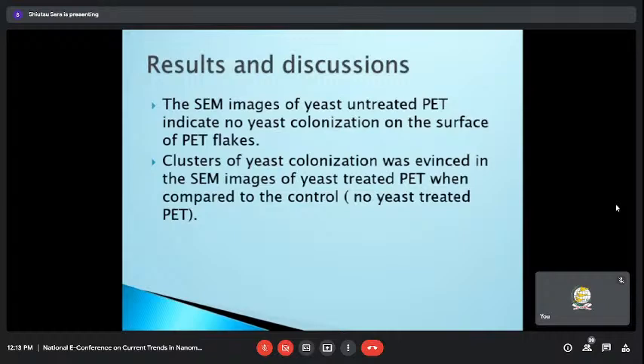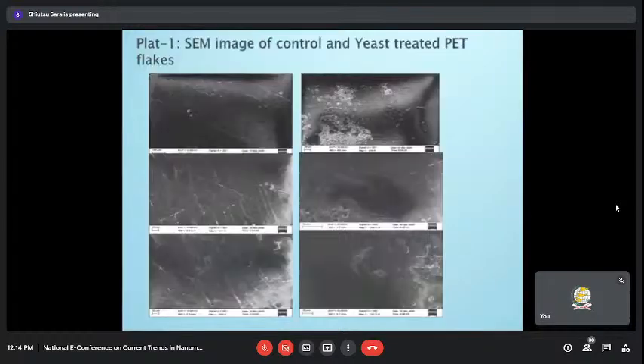Coming to the results and discussion, from the experiment which we have performed, from the SEM analysis method, we have found that there are two samples, one treated and the other untreated. The sample which we treated with the bacteria yeast showed colonization of yeast. Whereas the other sample, which we did not treat with anything, showed nothing. There was no colonization of yeast or any bacterial or fungal colonization. This is evident from the pictures shown here. This is the comparison picture of the treated samples as well as the untreated samples.